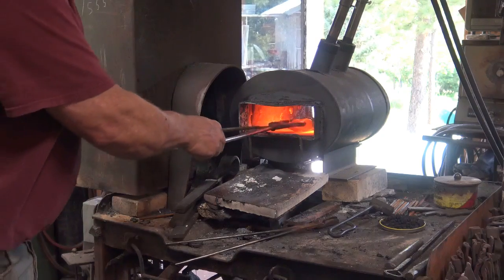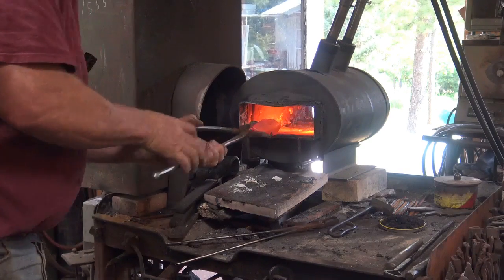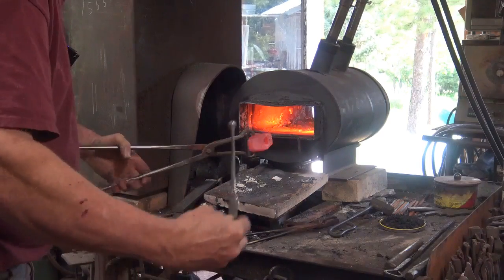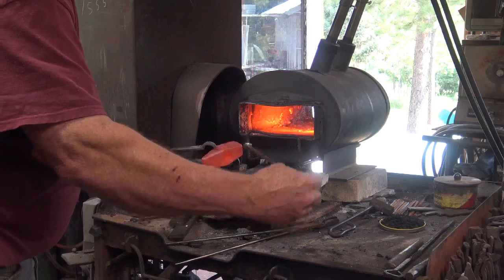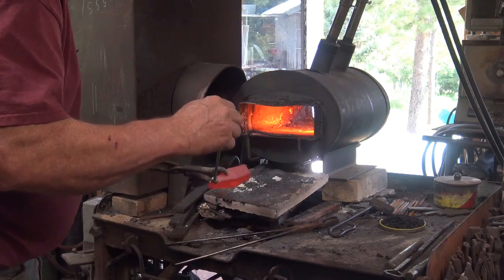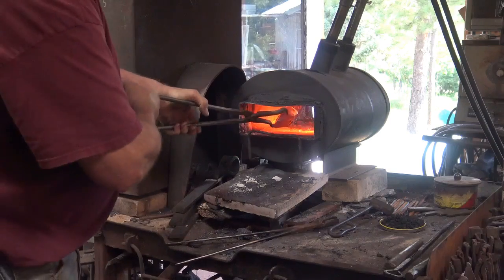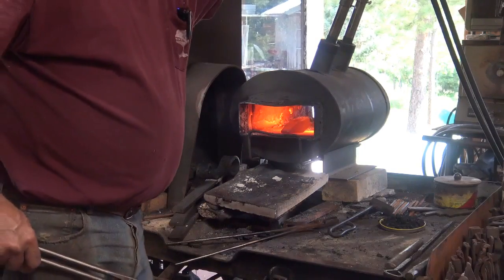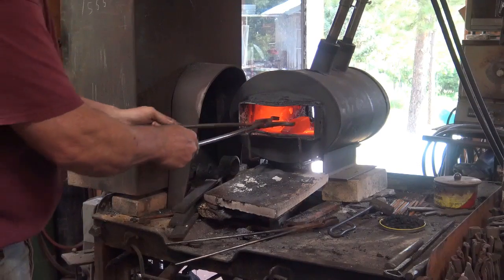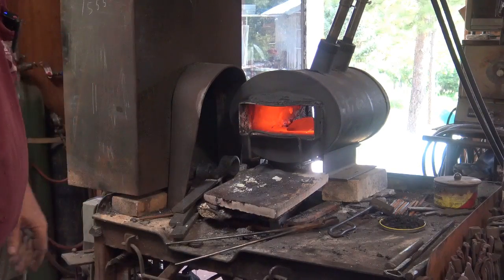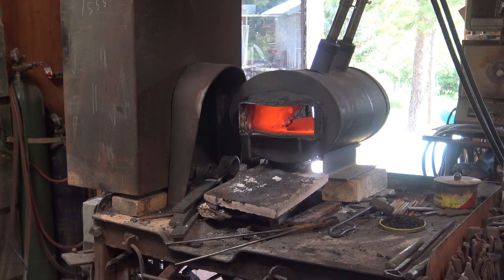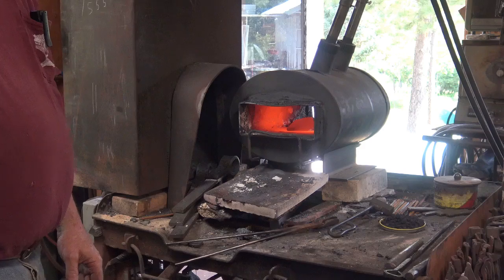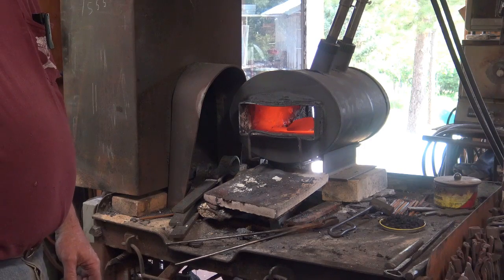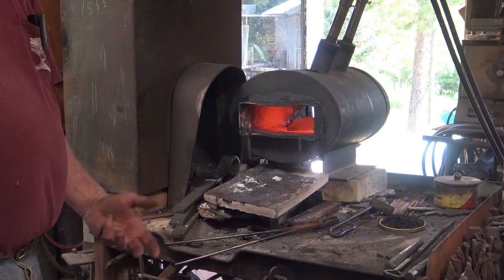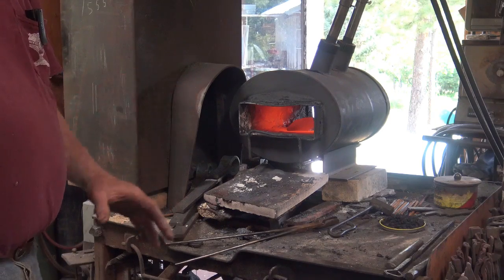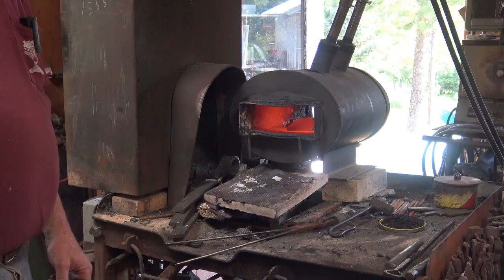Okay, we cycled the forge on and off a few times. It's getting much more evenly hot now. And my magnet doesn't stick, so that's probably about right. I'm going to let it soak one more time with the forge off, just to guarantee it's heated evenly all the way through, but I don't want to get it any hotter than it is right now. On the other hand, you should always quench at a rising heat. You don't want to let it cool down to critical temperature. You want to be bringing it up to critical temperature and then quench it. If it's cooling down, you've already gone too far.